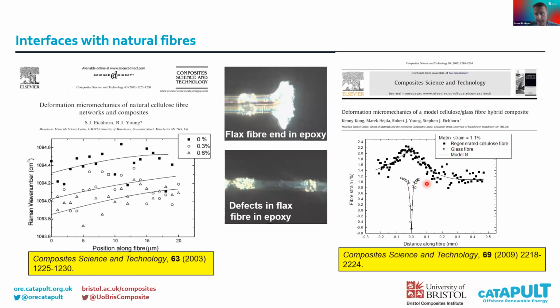This is perhaps one of the better techniques that we can develop here, where we have a glass fibre and a natural fibre close to each other, and we're able to see how a defect in the glass fibre interacts with and generates a stress concentration in the natural fibre. So we're able to do local mapping of how fibres interact with each other. If you had a hybrid system where your fibres were in close proximity, you could look at both the glass and the natural fibres together.